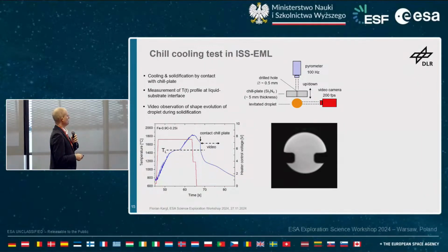So you have the sample, you heat it up, you melt it here, you see the melting plateau, you overheat it, and then you start cooling. So you switch off the heater, you see that curve here, heater switched off, sample starts to cool, and then at a certain point in time, still in the liquid state, you contact it with this chill plate that comes from top.